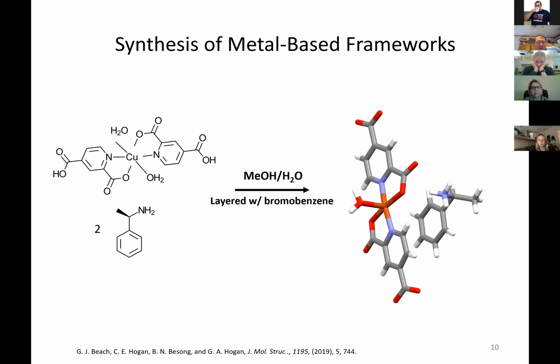Some of the take-home messages from this paper: if we take our copper complex and change our amine to a chiral-based one, called alpha methyl benzylamine, again using 2 equivalents of it, we get that same acid-base transfer, and we generate this little crystal structure after we allow it to crystallize in solution.